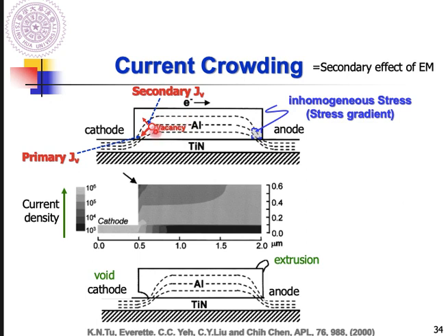So you want to push the vacancy out to reduce the resistivity of the electrical path in these materials. So for these reasons, some of the vacancy will be pushed toward the region with lower current density. So the direction will be the gradient of the current density toward this way. So we sometimes will observe some void form in the low current density region.